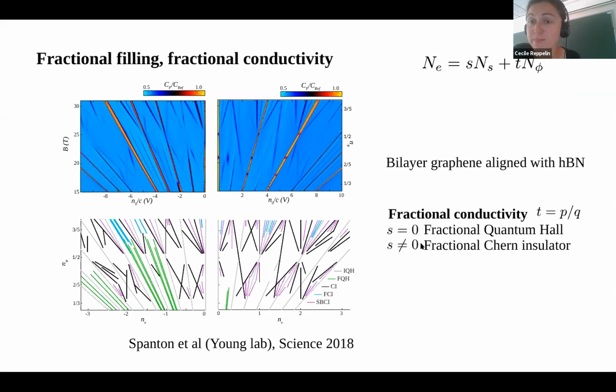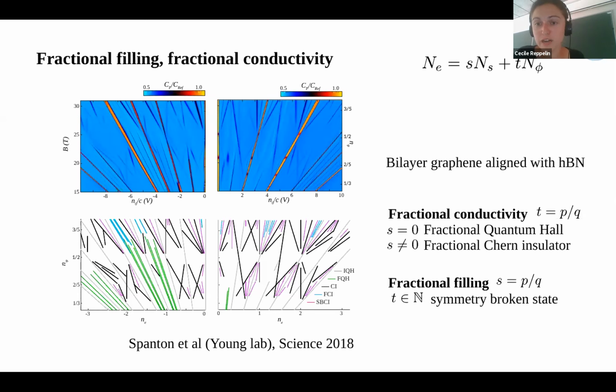you obtain your fractional quantum Hall effect by filling a Chern 1 band that comes from the superlattice, and we'll call that a fractional Chern insulator, because there's no way to explain the phenomenon without the reasoning including the superlattice. Another option is to have a fractional filling. And in that case, you don't necessarily have a fractional conductivity. You could also have a symmetry broken phase that has an integer conductivity. So that corresponds to the pink line in this diagram that the authors have called symmetry broken Chern insulators. So you still have probably a non-zero Hall conductivity. T is non-zero, but not fractional, and a fractional filling.